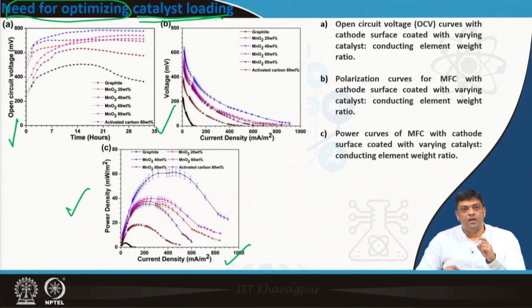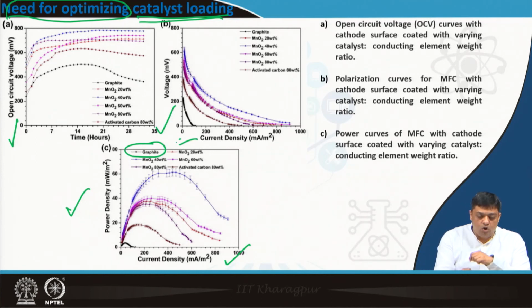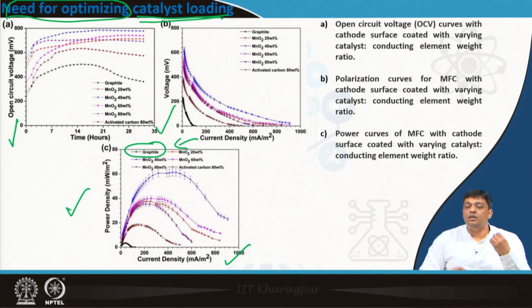You can see in this case we have used graphite as the electrode on which MnO2 has been loaded as the catalyst, and it is different. Why? Because we have not used platinum. The performance is very similar, maybe slightly less in terms of power densities, but MnO2 is much cheaper than platinum.